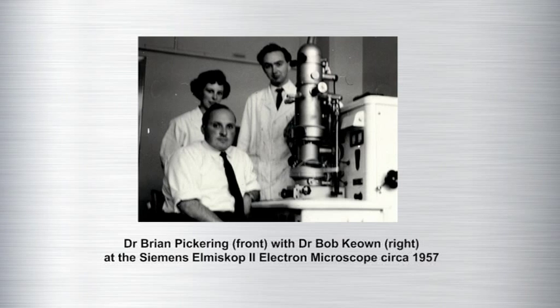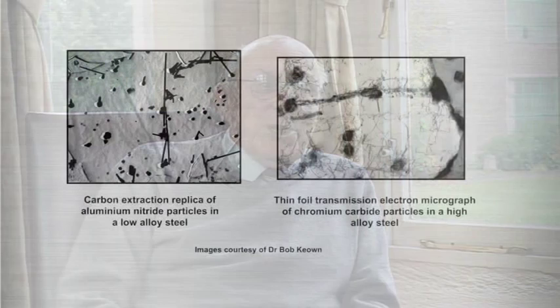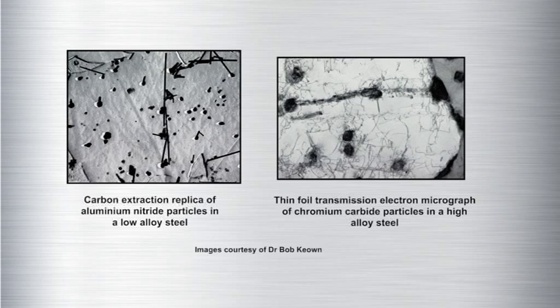But in fact, it was excellent for doing replicas and extraction replicas in particular. And we developed the extraction replica techniques to a fairly high degree. It was only later, and Bob will remember this himself, that he spent a month at least trying to make thin foils of all sorts of materials, because it was very difficult to make thin foils to use transmission electron microscopy with them. You could get quite remarkable results using good extraction replicas. So that's how we used it. The microscope was delivered by Siemens to these laboratories.